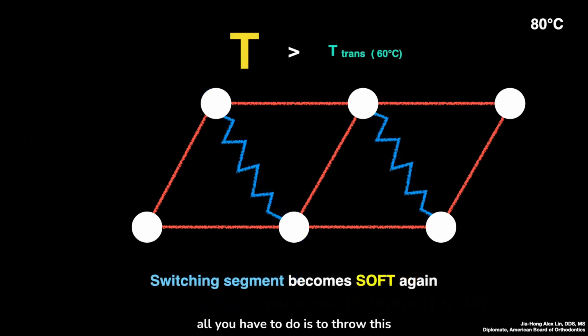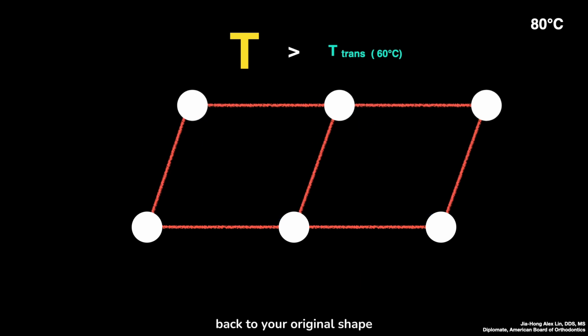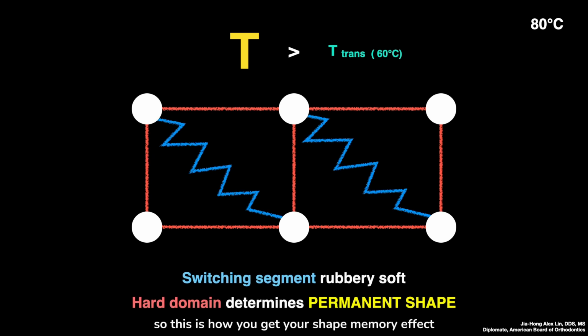All you have to do is to throw this deformed aligner into hot water and soften the switching segments. Once they become soft again, the red lines, the net points, are in charge of holding the shape of the aligner and will gradually pull the aligner back to its original shape. So this is how you get your shape memory effect. And this is how these shape memory aligners are revitalized and their force, the rigidity, is reboosted.